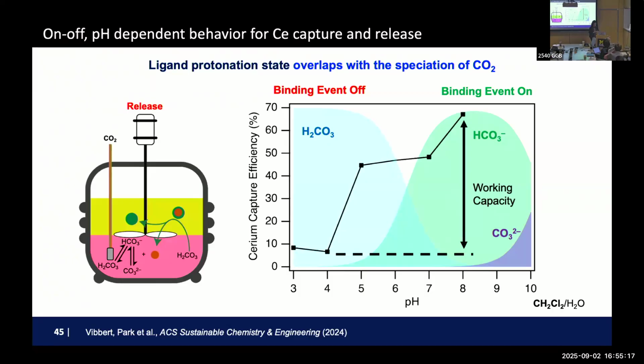And then if you lower the pH to 4, you will release. In fact, in the mining industry, it's called liquid extraction. So in order to do liquid extraction, you put in a lot of ligands and these collectors, and then it moves all the metal ions into the organic phase. Once you get the organic phase loaded with metal, you put strong acid in to do an acid wash. Then your metals come out with the acid.